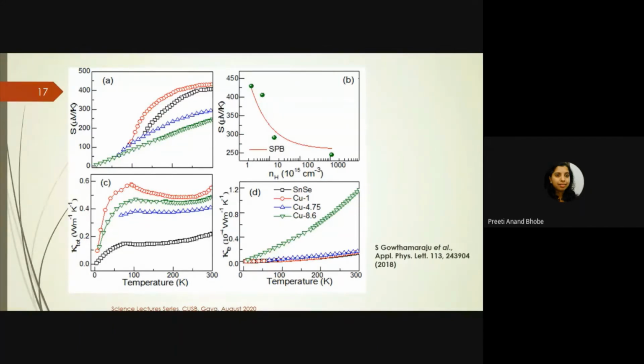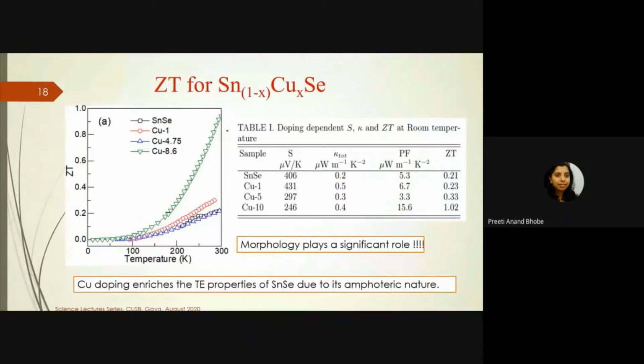But the thermal conductivity improves, because you are putting in a metal. And the improvement is basically because of the electrical part of thermal conductivity. Interestingly, its effective mass in the band structure almost remains the same; it follows a single parabolic structure. So in the band structure as such, copper is not making drastic changes to the Seebeck coefficient of the material. And hence, now if I look at the ZT, I do get an improvement in the ZT for 10% copper, or 8% copper, but I have to keep in mind that it comes at a cost of some small copper impurities of a second phase also forming.